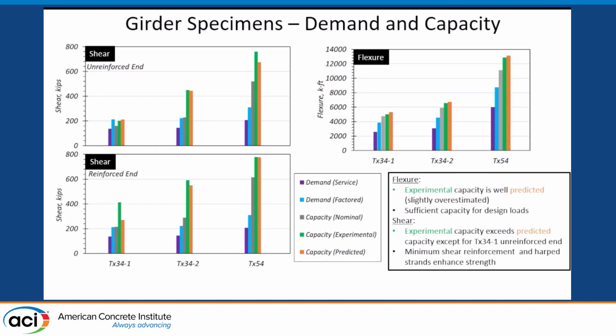And then finally, this slide is just a little bit of a comparison of when we tested the 3 different girders: in shear at the unreinforced end, the reinforced end, and then in flexure. And mainly, I just want to point out that the experimental capacity was either higher or very close to the predicted value. So we have a good understanding of how to predict the strength of these members. That was validated from the experiments.